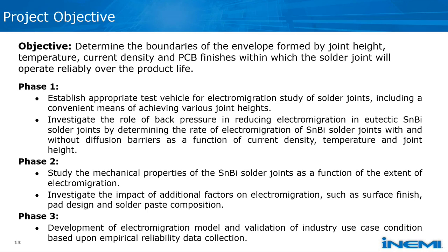Electromigration in solder bumps can be modeled with a finite element tool called COMSOL, C-O-M-S-O-L. The migration of vacancies themselves can be modeled by solving a transport equation which includes flux contributions due to vacancy gradients, electric field gradient, hydrostatic stress gradient, and a temperature gradient. In a broader scope, this COMSOL tool provides the ability of generating time to failure, TTF, prediction for different sizes of solder bumps in a range of current densities and temperatures. Next slide.